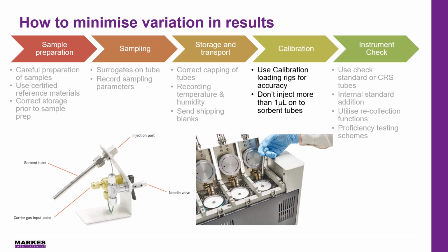Use calibration loading rigs for accuracy when injecting standards onto sorbent tubes, and be sure to only inject 1 microliter onto sorbent tubes to negate the solvent effect. In addition, you can inject a standard into the 4 chambers so you can compare the results of all 4 chambers to ensure that they're behaving the same.